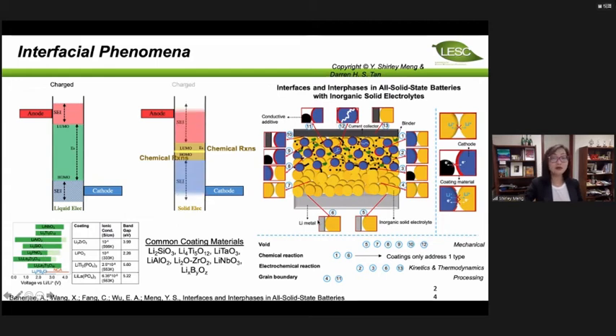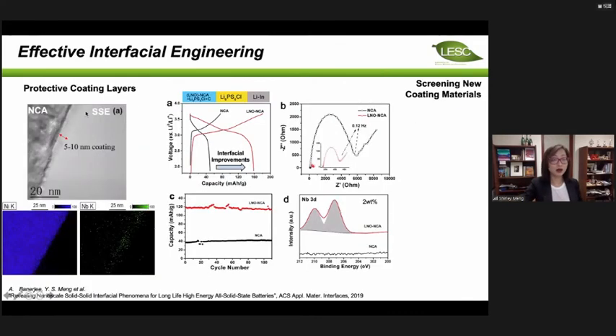In terms of coating, a 5 to 10 nanometer conformal coating, material scientists have many ways to achieve that. And indeed, with the sulfide based electrolyte and the nickel based cathode, if you do not engineer the interface, you cannot utilize the cathode very well, and you cannot cycle the cell very well. This particular coating here is lithium niobate oxide, which was released by Toyota many years ago, and they already have patents, but it doesn't matter.